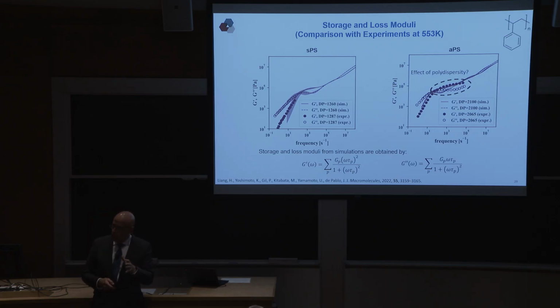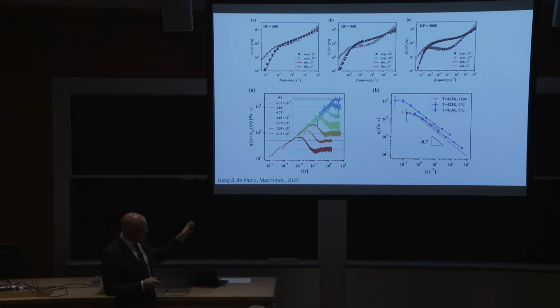So after a lot of thinking, we started to think that the origin of these discrepancies had to do with the polydispersity of the samples. In all of the calculations that I'm showing you, all molecules have the same size. And of course, in experiments, that is not the case. So we went back to the drawing board. We incorporated all of these polydispersities very precisely. Every molecule in the system has a different size, wide distributions, et cetera. And when you do that very careful work, you can actually achieve fantastic agreement with experiments. It's quantitative, both for the complex and relaxation modulus, for the viscosity, for the molecular weight, and for elongation or shear flows. So we're very happy with how this works now.